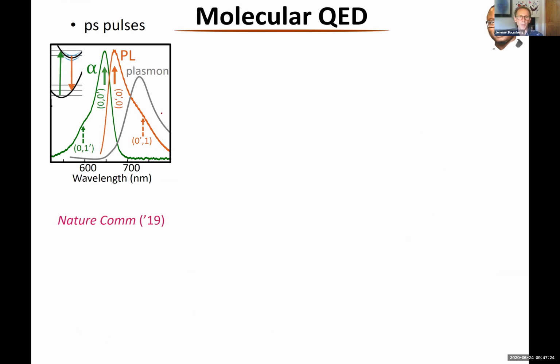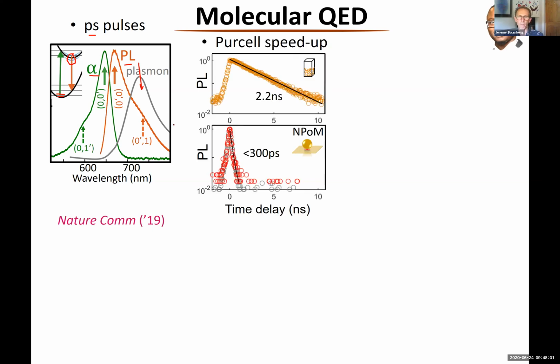What we can also do is show that these are actually really quantum emitters. So we can do the same trick, and now we're going to excite the system with a pulse, which I'll show you why we do. So these are slightly different dye molecules. Basically, the absorption of the dye, that's the absorption, and this is the emission. And then we have to decide where we're going to tune our cavity. We have to decide if we're going to tune it to the absorption or the luminescence or somewhere along here. You can't get strong coupling in both the emission region and the absorption region simultaneously. You have to choose because they're different wavelengths in a molecule. So that's not so obvious.